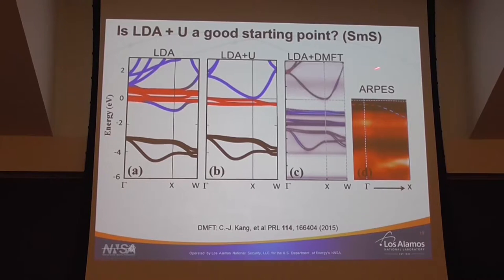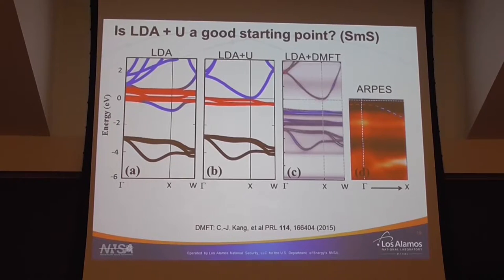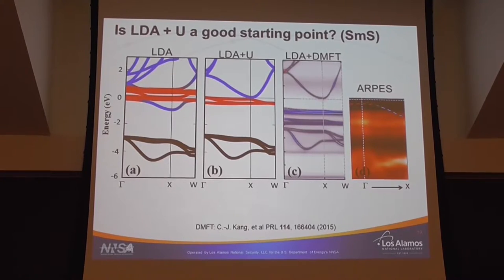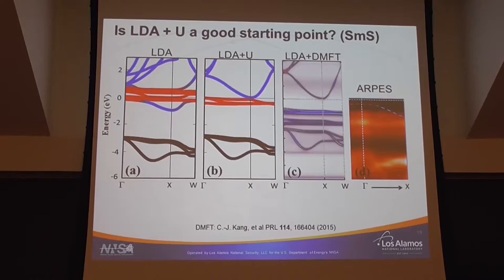Samarium sulfide, yes. So this was something that we were wondering about, because this is also another Kondo insulator type material, but it doesn't show any evidence for resistivity saturation. You can see here from the angle-resolved photoemission data, we don't have any evidence for any sort of nice topological surface state. In fact, we don't see any evidence for even the samarium d band inversion that you might